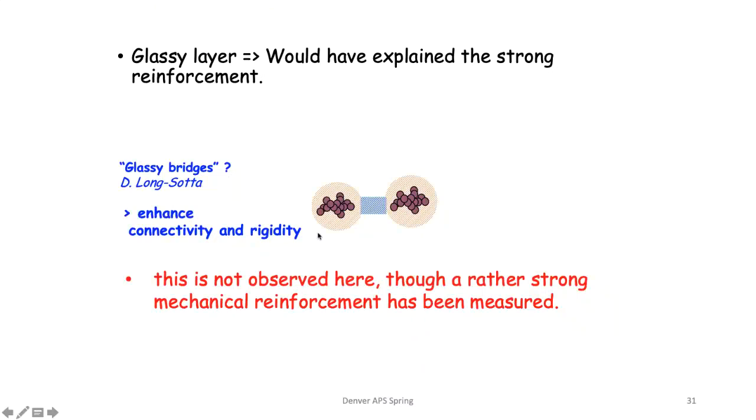And so this would be the origin of the reinforcement. In our case here, I think at least the grafted corona are not glassy. They are strongly deformed. So that means that this contribution of the frozen part around the clusters is not always visible. At least in this case, it is not.